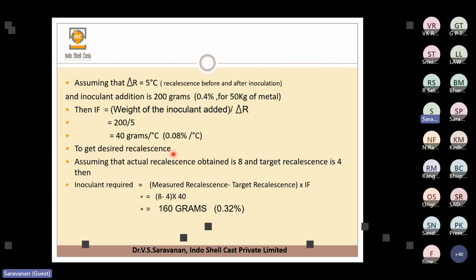So to get the desired recalescence, assuming that the obtained recalescence in one particular heat is 8, and our target is 4, I want to reduce 4 degrees. So 8 minus 4 times this inoculation factor, then 160 grams is required. This is what we can calculate based on the recalescence and the inoculation factor. So we can adjust the inoculation quantity dynamically according to the delta R, that is the recalescence. If the recalescence is already very good and low, then we can reduce the inoculant.